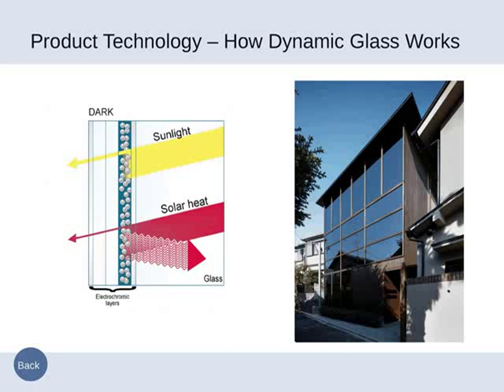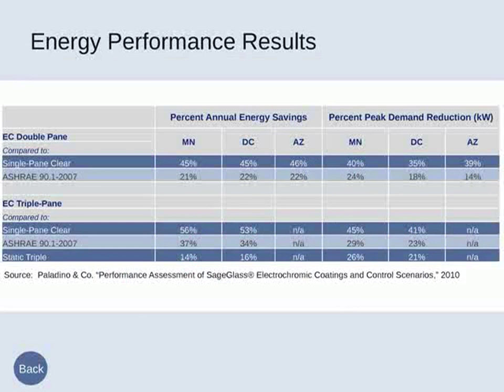This slide needs to be updated, but it compares single pane clear to the ASHRAE standard, showing the percentage of annual energy savings and the percentage of peak demand reduction. This was published in 2010, from the Palladino and Co. studies. Looking at the DC example, when you compare electrochromic double pane glass to single pane clear, you're looking at a 45% reduction in annual energy savings and 35% in peak demand reduction. Compared to the ASHRAE standard, it's a little less: 22% annual energy savings and 18% peak demand reduction.